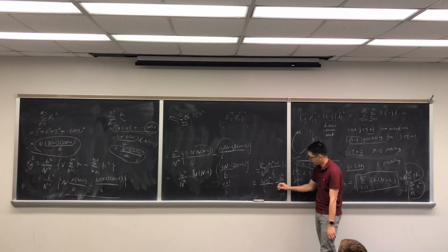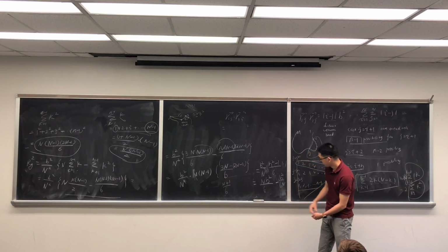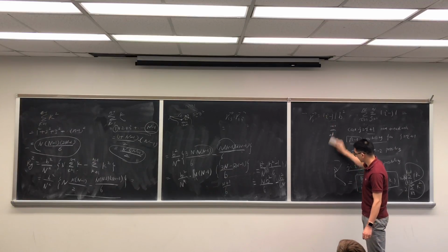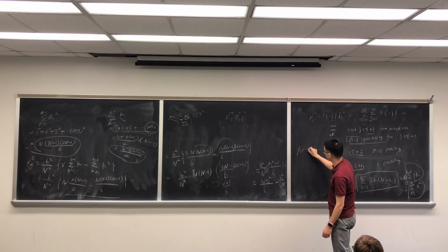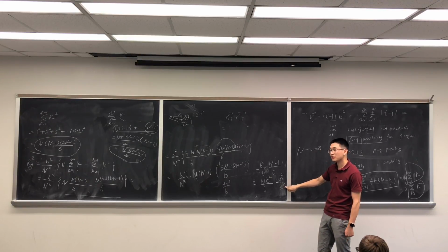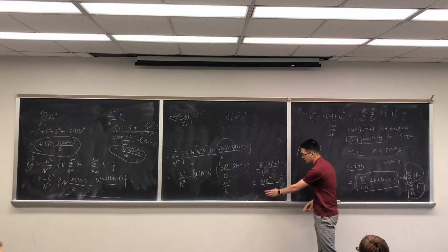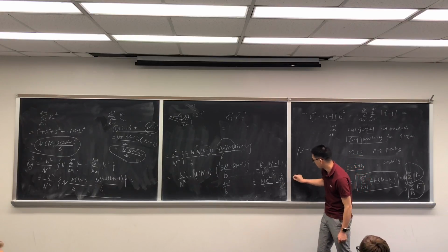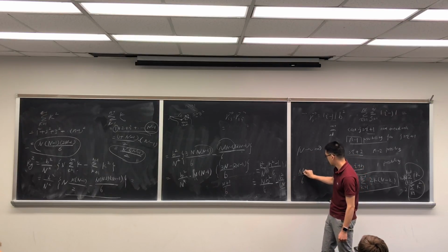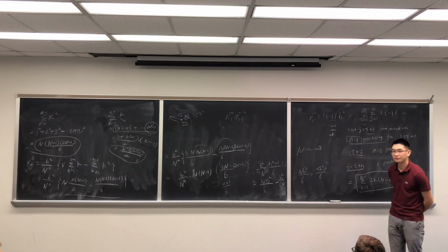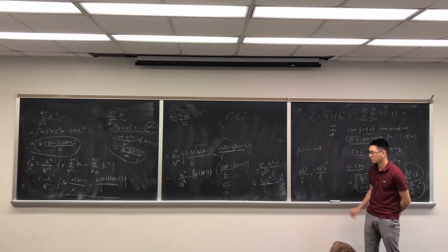And when n is a large chain, if n is very large, the second term, b squared divided by 6n, will be much smaller than what has been left on the left, right? So you basically simplify this equation to... voila, that's what we talked about at the beginning.